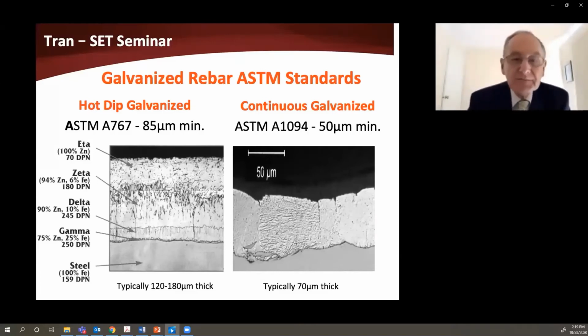microns or so thick. Now, ASTM A767 for one class of coating specifies a minimum coating thickness of 85 microns. This coating that's produced on typical steels generally is in the range from about 120 up to about 180 microns thick. And that is determined by the thickness of the bar that you're galvanizing. The key thing is ultimately there is still a layer of pure zinc, the eta layer, on the outside of this bright galvanized product that's 40 to 50 microns thick.